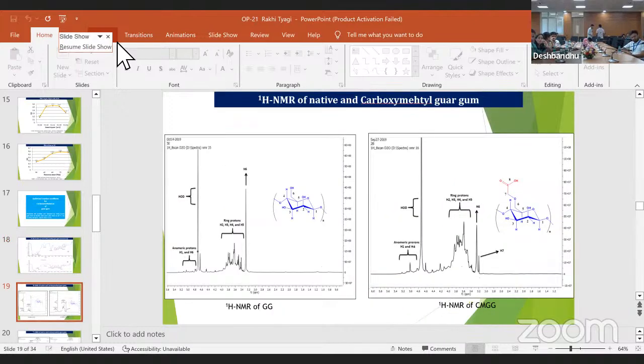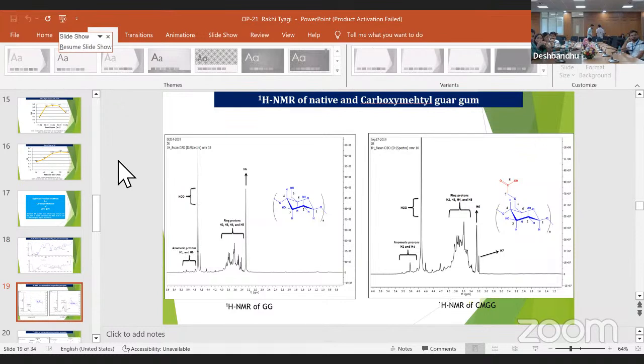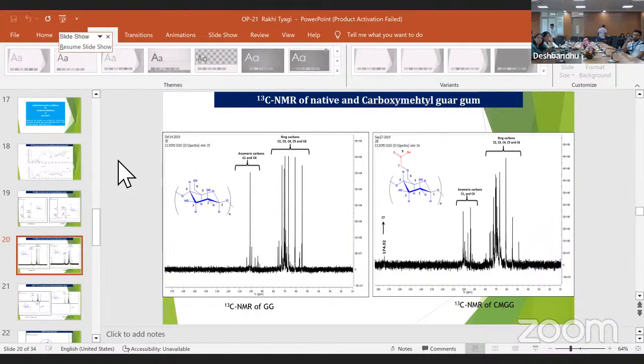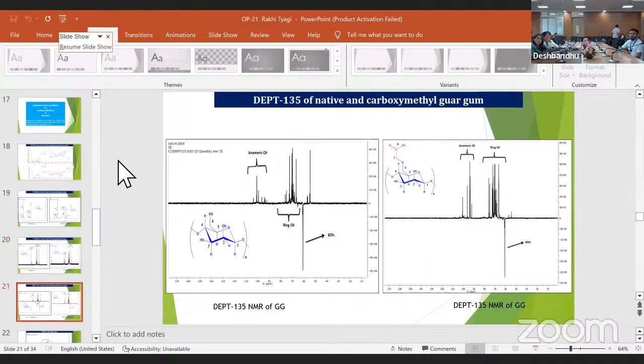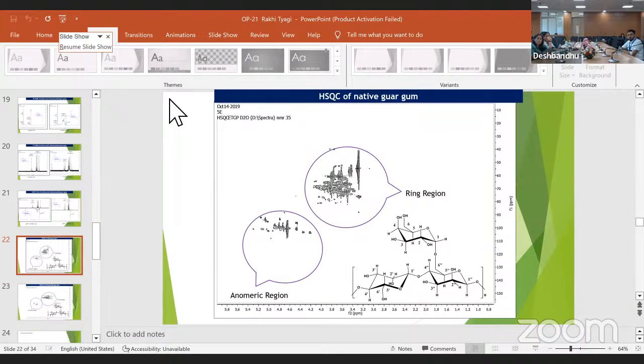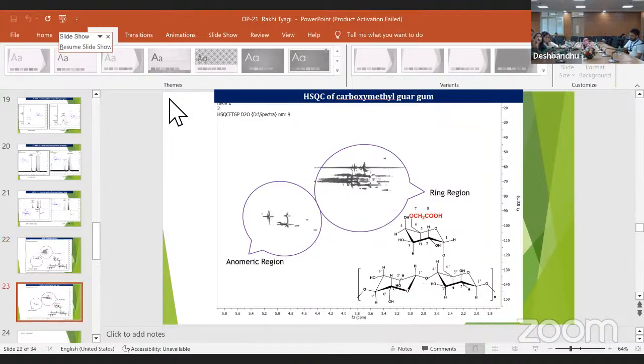This is the proton NMR spectra of the native and carboxymethylated sample. As we can see, in the native sample the peaks were concentrated in the anomeric and ring region, but in the derivatized sample, an additional peak was identified at 3.1, which was accounted for the introduced carboxymethyl group. This is again the 13C NMR spectra, where there is an additional peak due to the introduced carboxyl group. This is the DEPT-135 spectra for the native and modified sample. This is the HSQC spectra of the native guar gum. Here again, the peaks were concentrated in the ring region and the anomeric region. In the derivatized sample, the peaks due to the introduced group were not resolved as they merged with the ring region peaks.